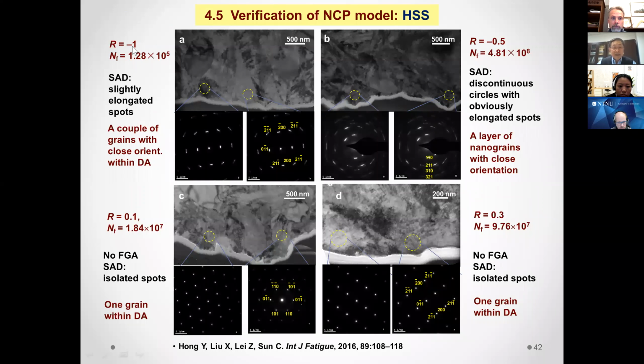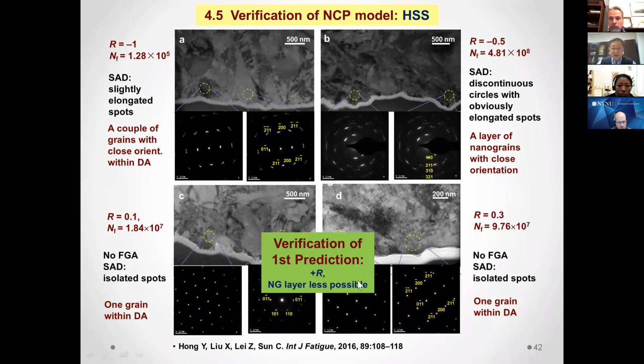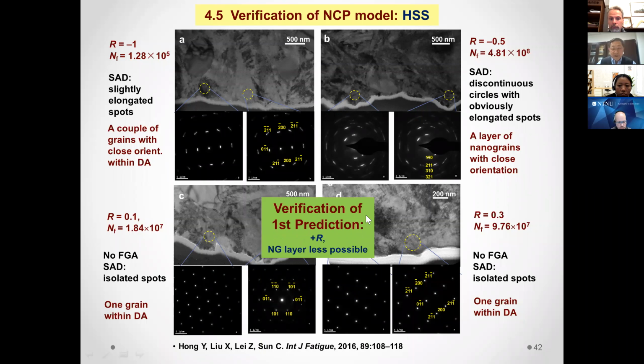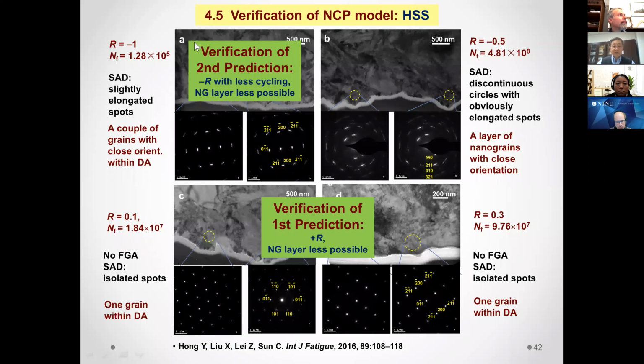We can see the diffraction pattern is a kind of slightly elongated spots, meaning there's a couple of grains in the diffraction circle. And for the stress ratio 0.1 and 0.3, all the diffractions are isolated spots. So this is the verification of the first prediction. This is the verification of the second prediction.